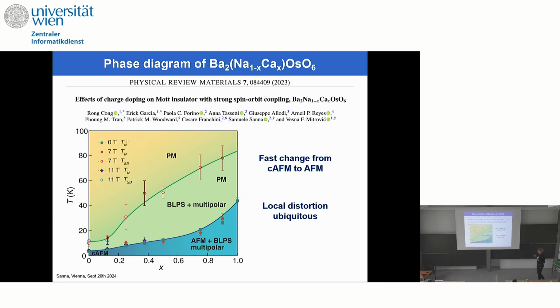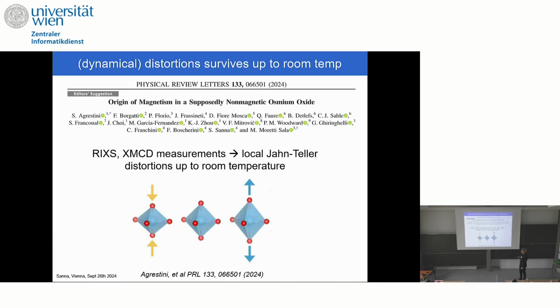So this way we demonstrated not only that we have a fast change from canted-antiferromagnetism to antiferromagnetic, but that the local distortions are persistent in the phase diagram, and also that the transition temperature increases very much when we are in the doped situation. But ask Marco, yes, please.